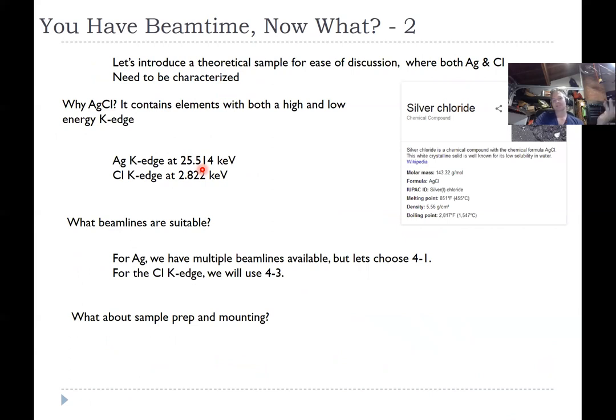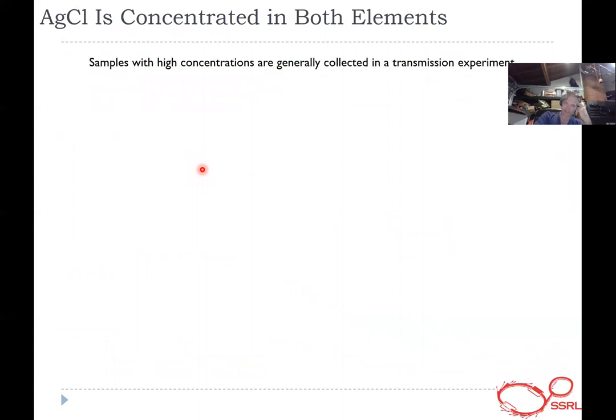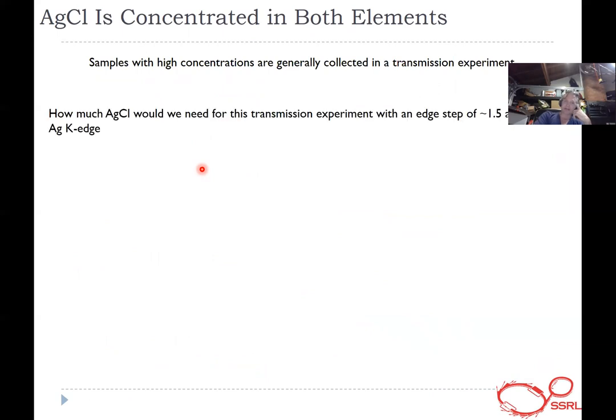So what next? What about sample prep? How do you mount these? Silver chloride is concentrated in both elements, and samples with high concentrations are generally collected in a transmission experiment. To get a ballpark of where you should start and how you should prep your sample: how much silver chloride would you need for a transmission experiment? You want an edge step of 1 to 1.5. We'll use 1.5 here.